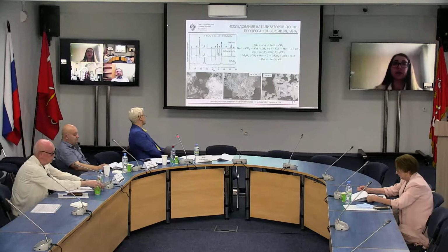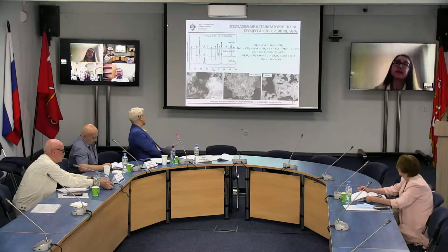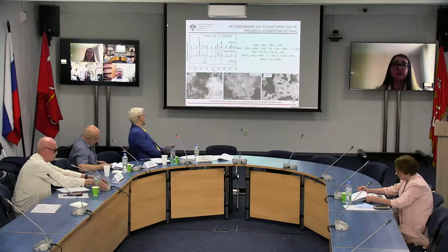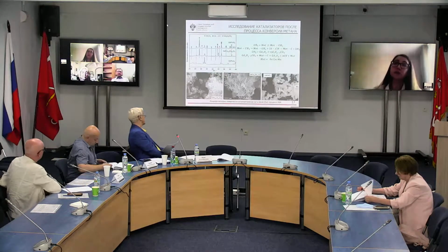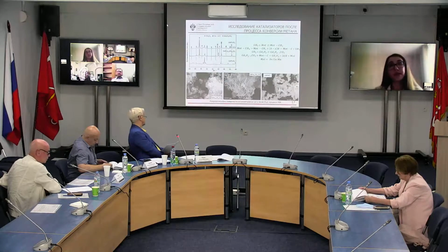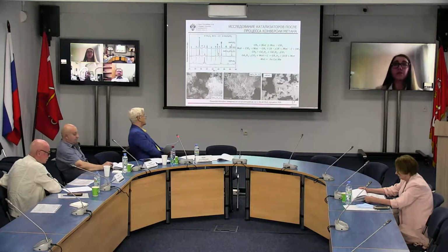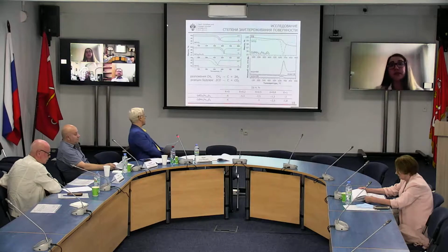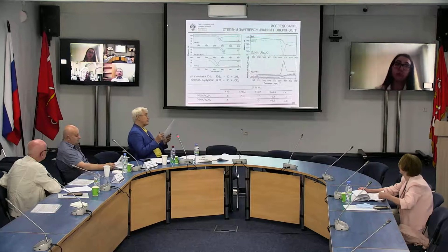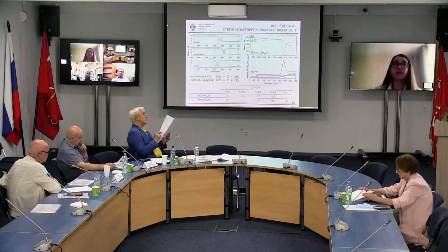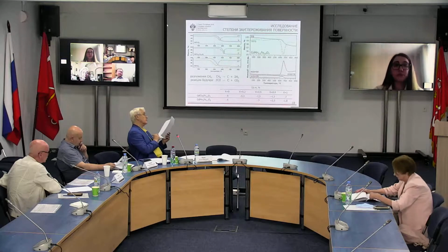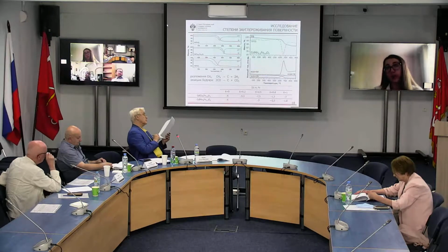Studying the surface of catalysts after catalytic tests demonstrated that the change in morphology associated with coking of crystallites happens during high temperature processes. And we have not just this coking on the surface, we also see filamentary-like structures. According to elemental analysis, these filamentary structures are represented by carbon. And during methane conversion, coke formation is one of the key reasons for deactivation of the catalyst. According to the temperature range of such studies, the formation of carbon happens due to some side processes, for example, the breakdown of methane and the Boudouard reaction.